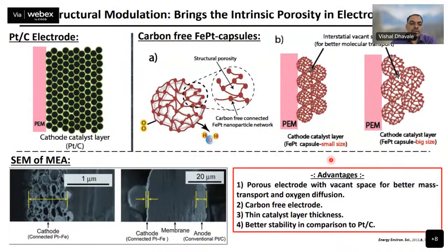So this material, the importance of this material being listed here, I already told. If you see the PtC electrode catalyst, we have very thick electrodes in the fuel cell system. If you use such nanoporous, nanocapsule structures, you can reduce the thickness with a similar weight loading of the platinum. Mainly important, these nanocapsule structures have different sizes, and we have worked with different sizes also. With different sizes, we can expect different sizes of the interstitial vacant spaces, which can be used for better water management and better mass transport during the fuel cell application. So there are multiple advantages of such a nanocapsule structure.